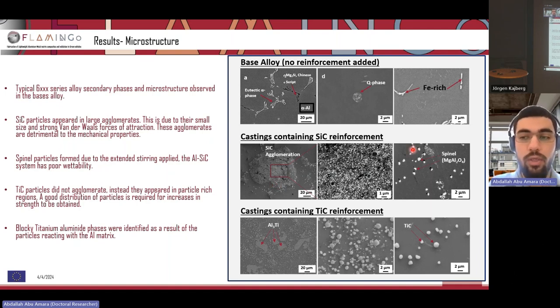And we also saw the spinel phase, the MgAl2O4. Essentially, the reason why these particles appeared is because of the extended stirring time. The longer we stir, the melt begins to oxidize and we form aluminium oxide. Then this aluminium oxide can react with the magnesium, which is inherently present in the alloy, and it can form spinel.